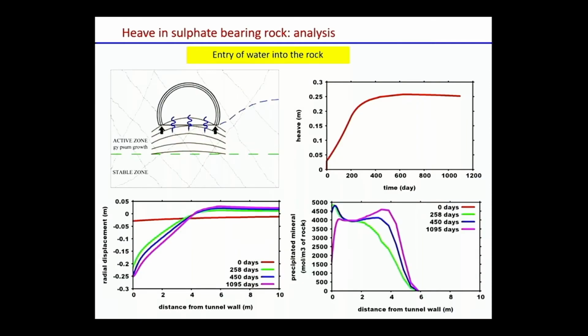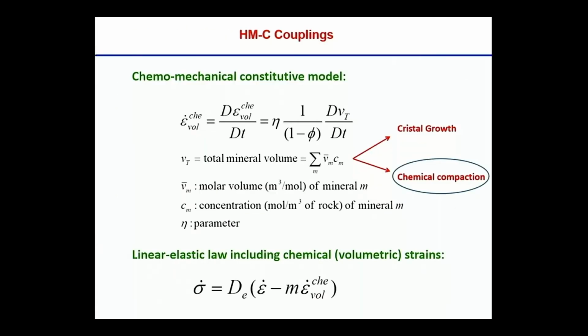So we did some simulations, and we could model this expansion. You can see that the active zone, which is one of the questions that we have to solve, is about 6 meters from the wall, where we have some increase of stress, some heave. This was the first problem where we tried to model this phenomenon of stress related to chemical reactions, and it is published, and there are other mechanisms that we have also published that I will not detail here, but we can see in the literature. But the other phenomenon that I would like to present is chemical compaction.